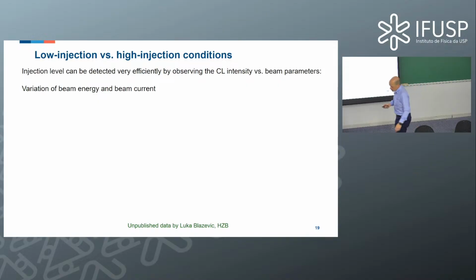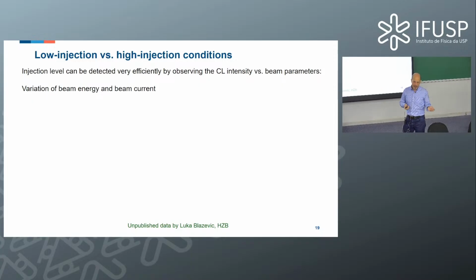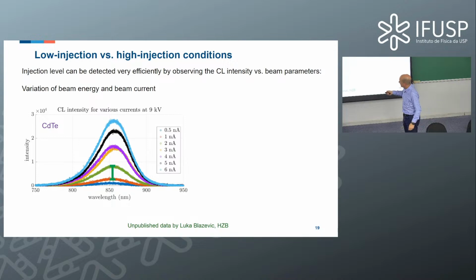So what we have to do in order to perform this model is to really take care of the injection level. Because the recombination is different when you generate more electron hole pairs by the electron beam than you have in terms of the net doping. So low injection means we're still in a position where the density of the generated electron hole pairs is smaller than the net doping, right? Otherwise it would be higher. And you can detect a transition normally by a very strong increase in the CL intensity. Why is this? It's because the CL intensity is radiative recombination. That's what we see. It's a radiative recombination rate. So the higher the recombination rate, the higher is the CL intensity.